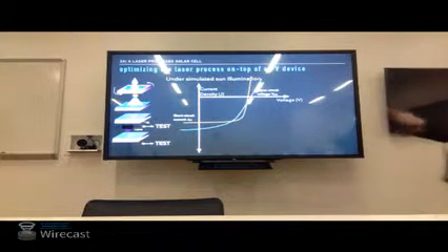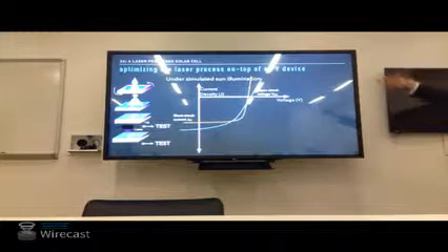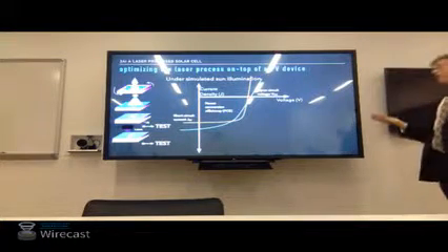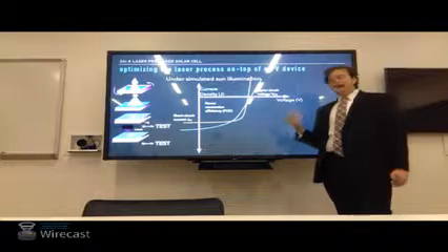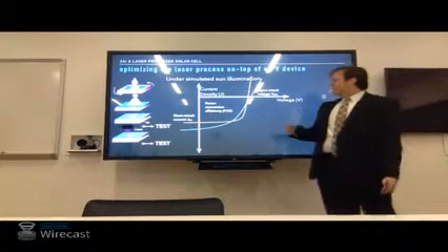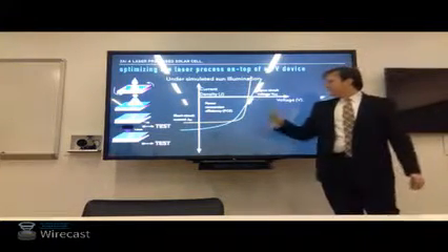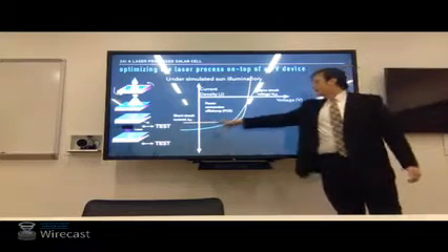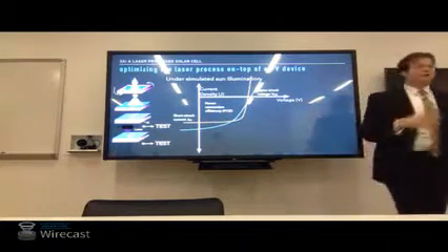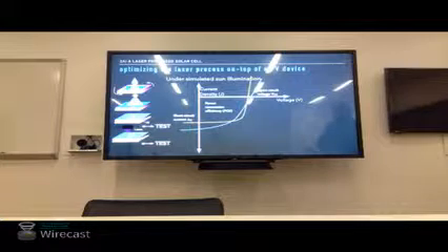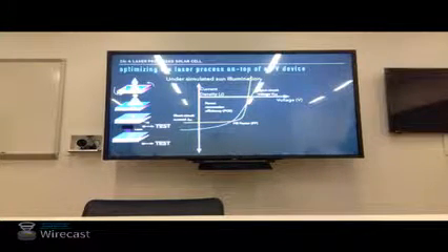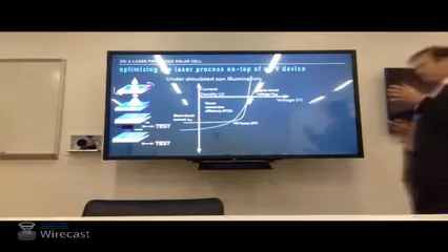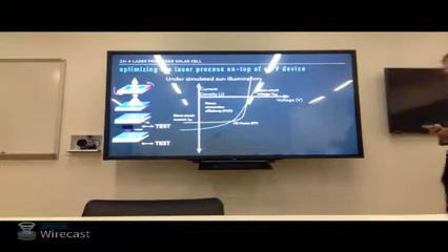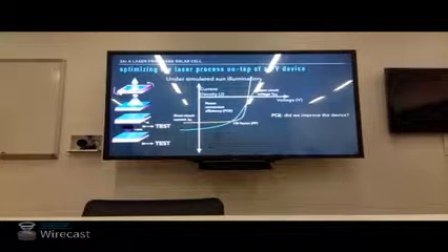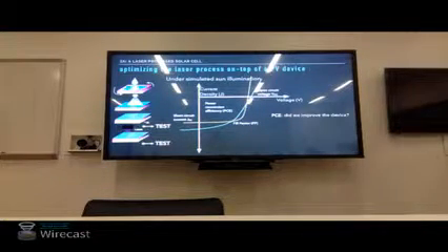Open circuit voltage, where the yellow has a lower open circuit voltage, but then power conversion efficiency, which is kind of our maximum power we can get out. Again, power is kind of our x times f of x here, if you will. So it's our current times our voltage, we get a power density. And our fill factor is a geometric factor that relates the open circuit voltage, the short circuit current, to the power conversion efficiency.